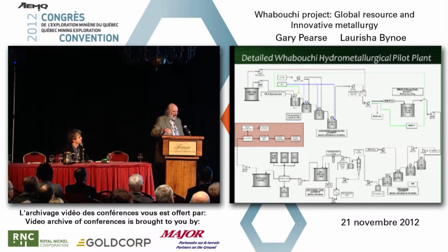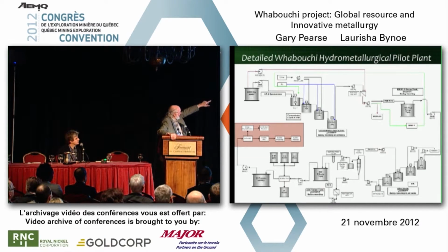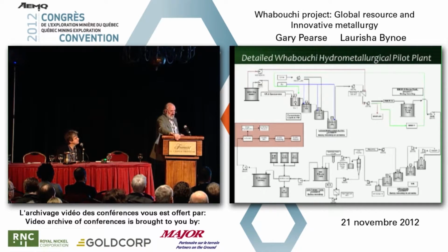Oh, there we go. This is just a flow diagram of the process, and the first part is pretty much standard in that it's the leaching and recovery of the lithium from the acid bake concentrate. And there we end up with a product where we've removed iron and aluminum pretty much completely, but we have to move it on to a secondary impurity removal where we raise the pH with, in our case, lithium hydroxide, which we can then recover again.